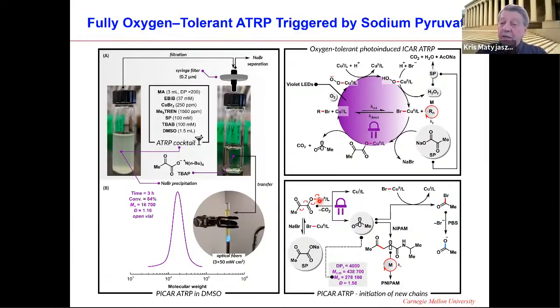So can we run the reaction in, let's say, DMSO or DMF? And this can be done in the presence of the phase transfer catalyst. So we are using here tetrabutylammonium bromide, which exchanges cations and forms this organic soluble pyruvate with tetrabutylammonium bromide. And sodium bromide, which is formed in situ, can be easily filtered, and then you can get polymers, again, in a short time, good control of molar masses and low dispersities.